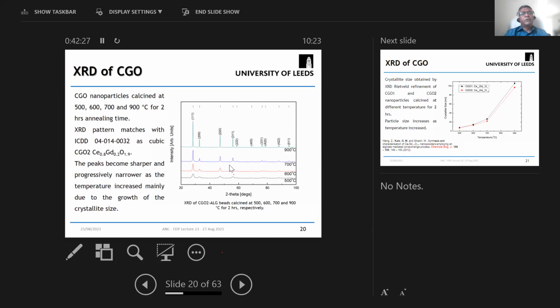And we calcined instead at 4 different temperatures, not knowing what will happen, whether it will form a single phase. And to our surprise, it did form a single phase cerium gadolinium oxide at 500 degrees Celsius itself. You can see that the peaks are very broad, but they are the same peaks as the fluorite peaks in the sample calcined at 900 degrees Celsius. And these are the peaks indexed from the standard diffraction pattern in JCPDS. So you can see that all the peaks are present, albeit at a lower intensity compared to that at 900, simply because of the tiny nature of the particles produced at 500 degrees Celsius. And you can see that the peak intensity slowly creeps up as you increase the temperature.